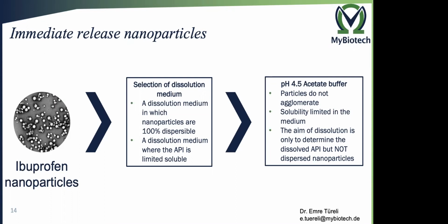We had only limited solubility in the medium because the solubility of ibuprofen is pH dependent, which means once the pH is increased, the solubility increases. If you do the same study at pH 7.2, you will directly get 100% dissolution. But if you do it at pH 4.5, you get only a limited dissolution of the API. And the result we were looking for was that we want to only determine the dissolution of the API, but not the dissolution of dispersed nanoparticles.